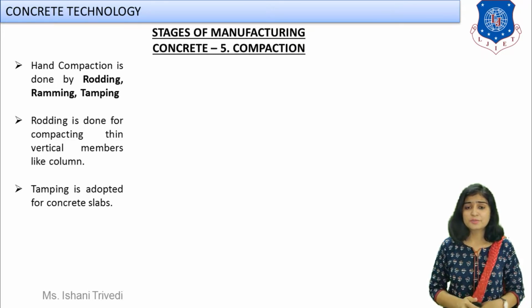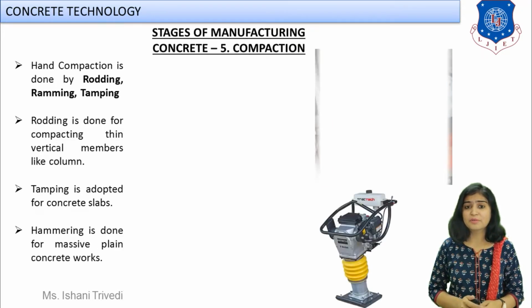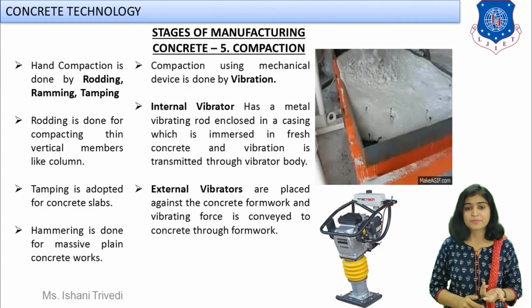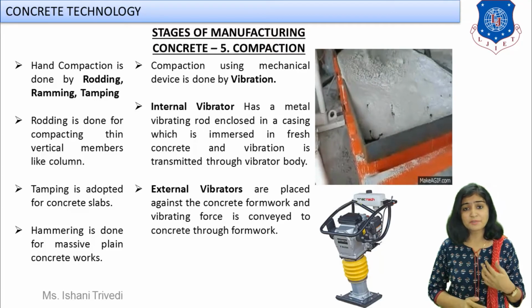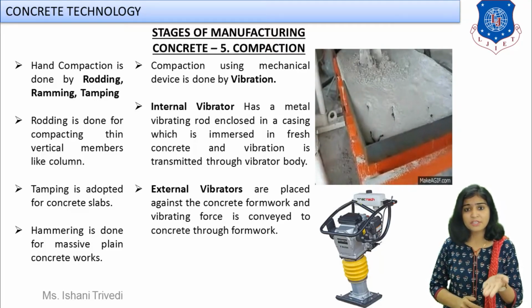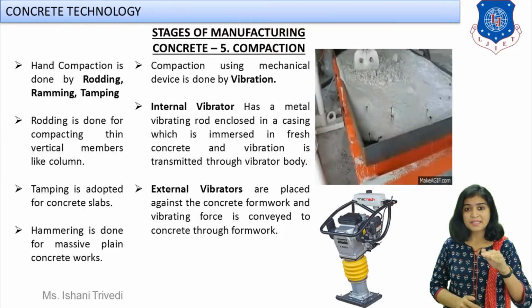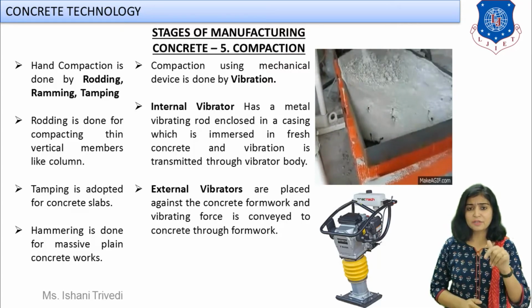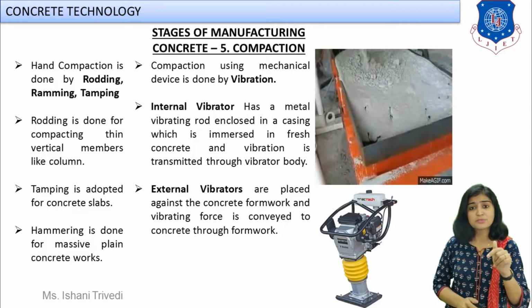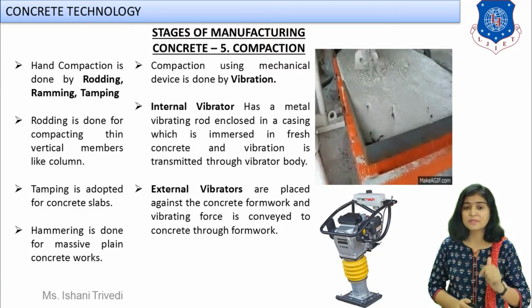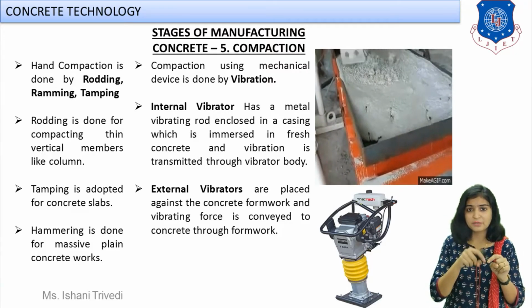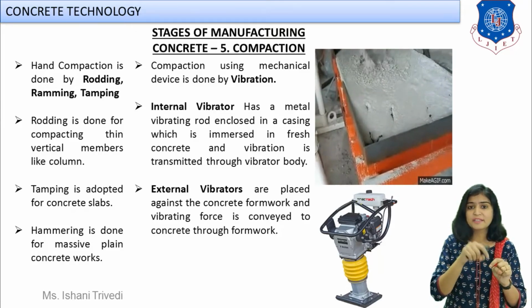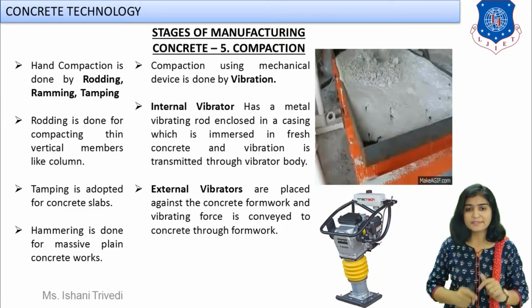But great care has to be taken that while carrying out the compaction by vibration, you should not over compact the concrete. Otherwise, because of excessive vibration, the water will come upside and the material will get segregated downwards. So it has to be taken care of. For a particular place, only 3 to 4 seconds of compaction vibration has to be provided for a particular point. You can cover the whole area by poking the needle at different places.